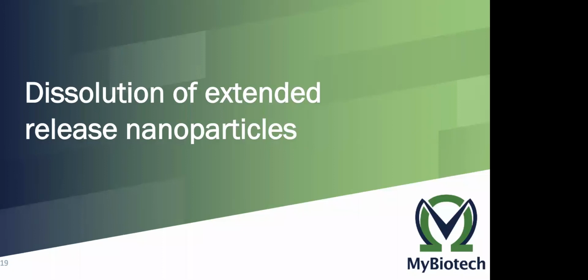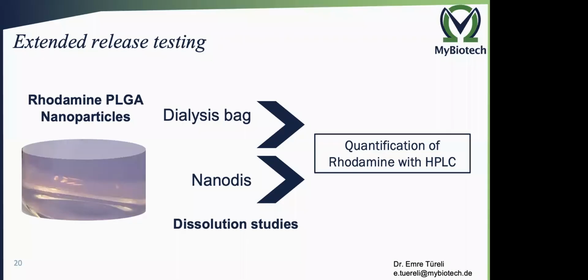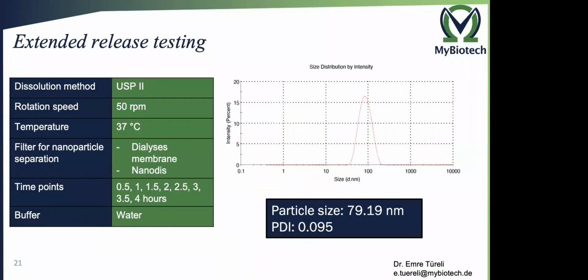We have also worked on dissolution of extended release nanoparticles. It's also an important thing, especially for the new formulations, these PLGA, PLA parenteral formulations, which are required to release in the body for at least 1 month or maybe even longer. So the dissolution of these nanoparticles also needs to be quantified. For that, we have used rhodamine PLGA nanoparticles. We have used two methods. The first one was a dialysis bag, and the second one was, again, the Nanodis. And then at the end, we quantified rhodamine with HPLC.